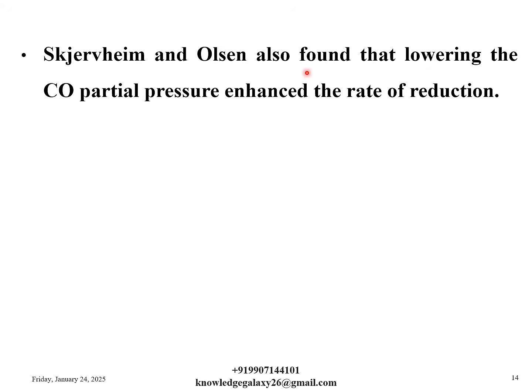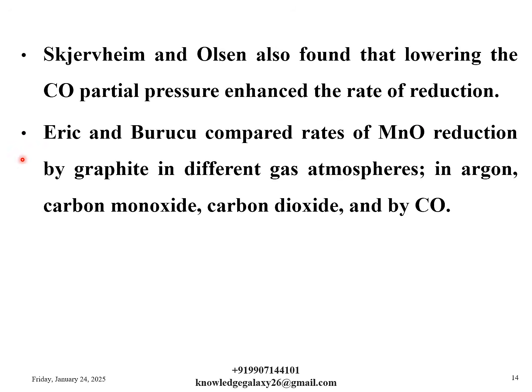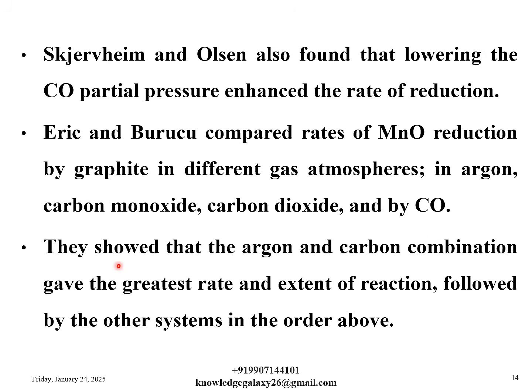Skjervheim and Olsen also found that lowering the carbon monoxide partial pressure enhanced the rate of reduction. Eric and Burucu compared rates of MnO reduction by graphite in different gas atmospheres: argon, carbon monoxide, carbon dioxide and CO. They showed that the argon and carbon combination gave the greatest rate and extent of reaction, followed by the other systems in the order above.